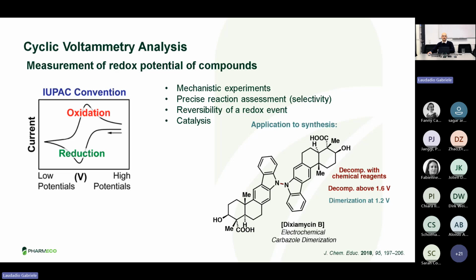For example, in the synthesis of dixiamycin B, the authors wanted to make this nitrogen-nitrogen bond. They tried several chemical oxidants, but none of them worked well. So they recorded a cyclic voltammetry analysis of the monomer, and they observed a redox event happening at around 1.2 volts. By running this reaction in potentiostatic mode at 1.2 volts, they managed to obtain the desired product. While if they moved the potential, for example, to 1.6, they observed complete decomposition, showing that cyclic voltammetry can be very useful also in a synthetic application.